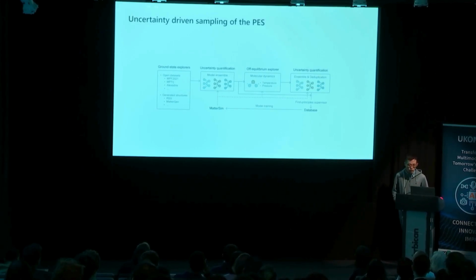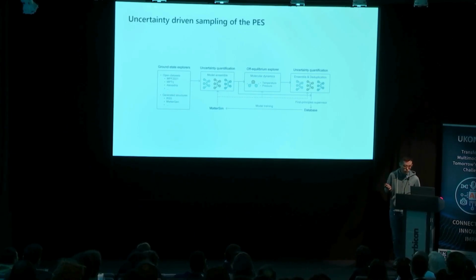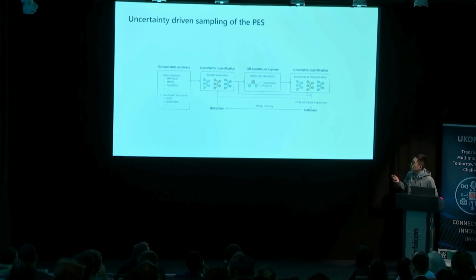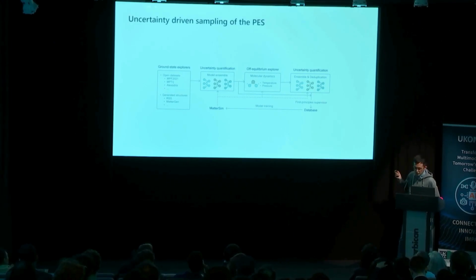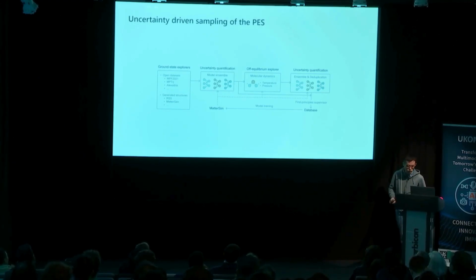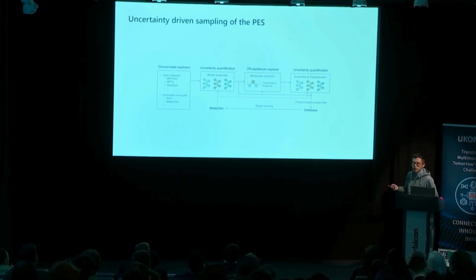So let me go into a bit of detail over how we built up this model. A key component of the model creation is sampling the potential energy surface with a lot of quantum mechanical calculations. We use active learning to guide the exploration of the space. We actually use uncertainty to guide the exploration. What we do is start with a few seed materials, and we sample points around them, and then we train a predictor which has uncertainty estimation components in it. Then, for all these candidates, we only run DFT on those areas which have very high uncertainty. So you only sample those uncertain points while you are running these large-scale DFT calculations. And this is iterated 5 to 6 times, until we get a very, very big data set.